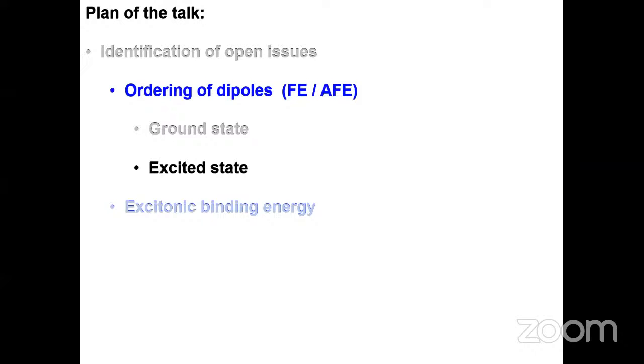We also looked at the excited state because there's this interesting story: you create an electron and hole. The dipoles are rotating, but now you've created an electron and hole. The electron gets attracted to the positive end, the hole gets attracted to the negative end of the dipole. So the dipole now has an electron and hole attached to it, and it might find it more sluggish to rotate. And if it freezes, then by dipolar interaction, it can freeze other dipoles. So it's not just the ground state. In the excited state, you may have a polar state.